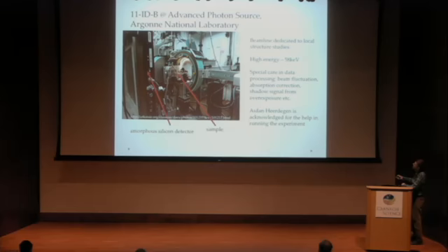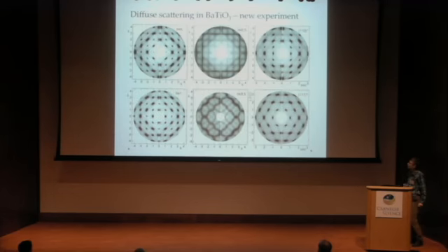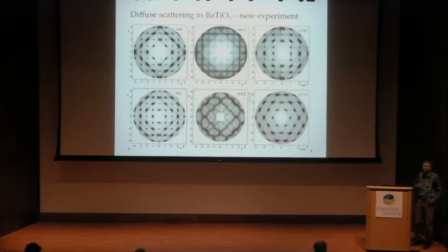Experimental setup. The experiment was done at Argonne at the 11-ID-B beamline with high energy X-rays, and the sample was somewhere here, rotating so that we can collect the whole reciprocal space diffuse scattering. There is an amorphous silicon detector, and here are the results. After some corrections and rescaling, calculating the diffuse scattering into orthogonal coordinates, you can then make a cut in any direction in the reciprocal space you wish, and you really see these nice diffuse lines going through the principal Bragg points, and you can, for example, look at the 1-1-1 plane, and you always still see this line.